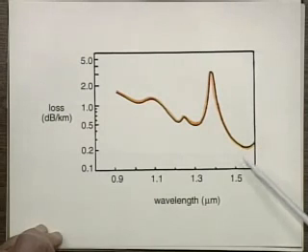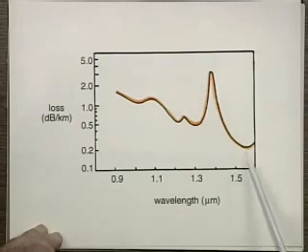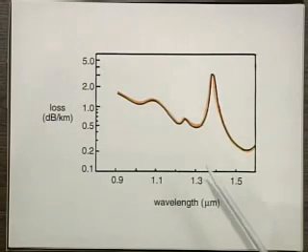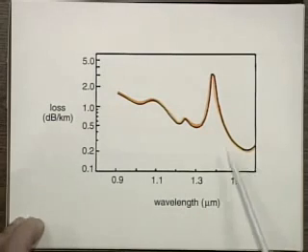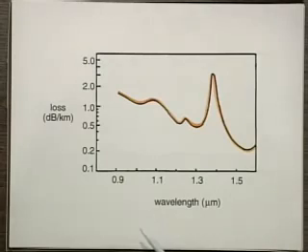If you want to reduce this loss from, let's say, 0.1 or 0.2 dB per kilometer, then you have to use other materials, materials whose material absorption is further into the infrared. So I'm afraid we're not going to get into the visible and have low loss because of the Rayleigh scattering. If we're going to do better than this, we're going to go further into the infrared, which means we have to have the right sources and components to work in the infrared and then deeper in the infrared.